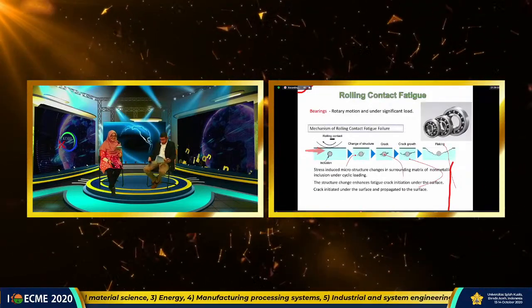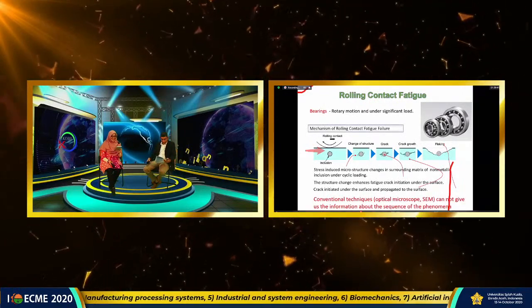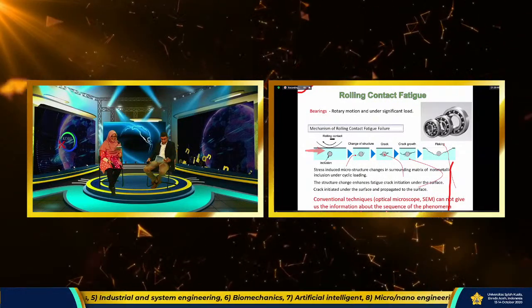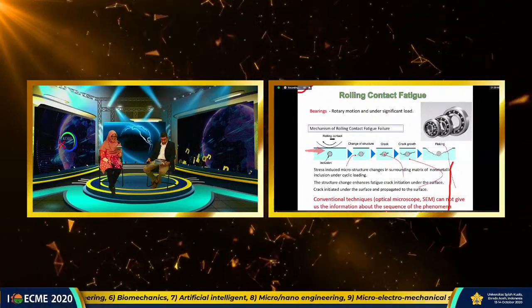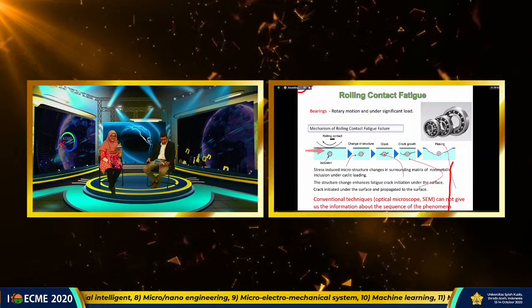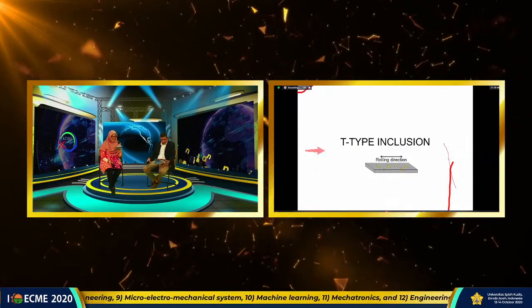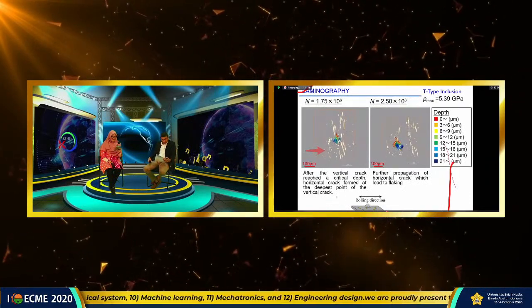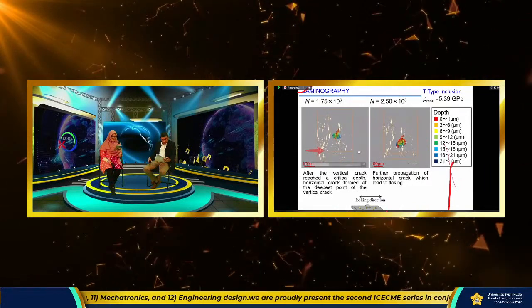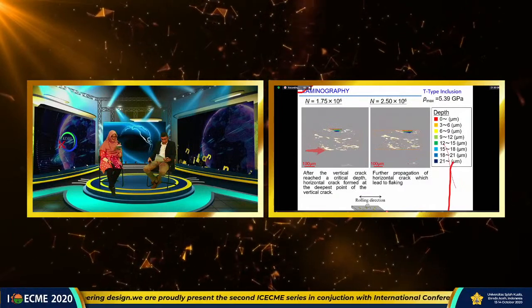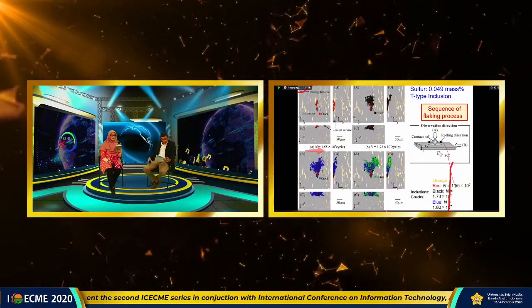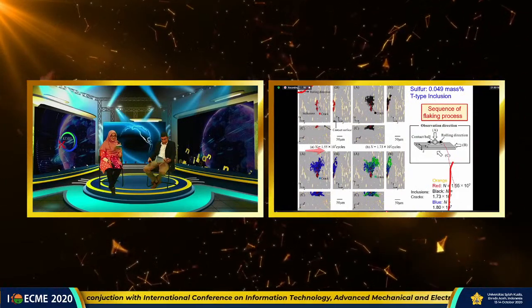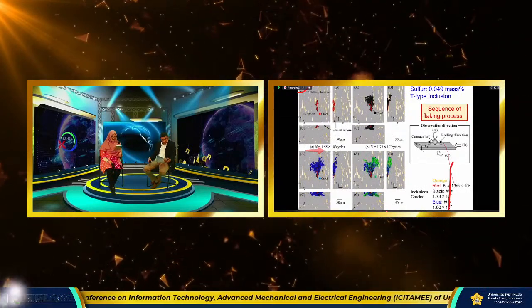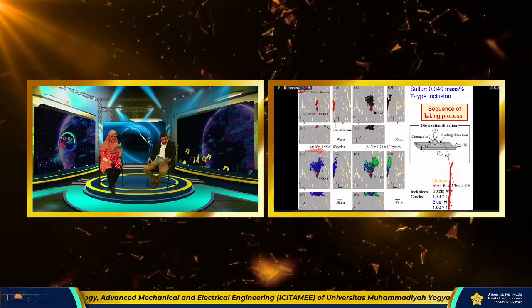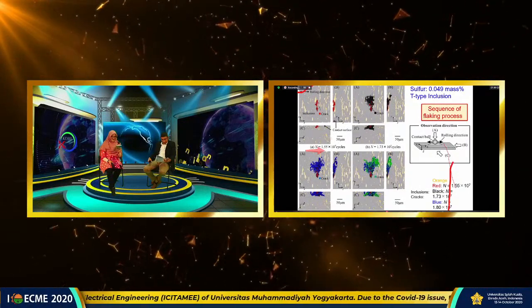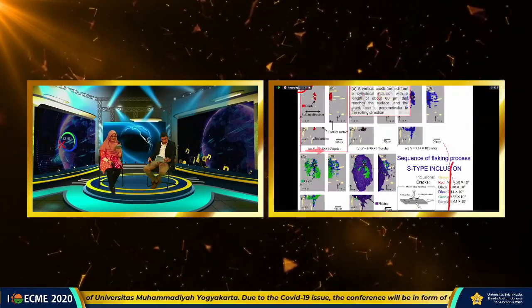So I skip this one. The mechanism of rolling contact fatigue is not observed directly by conventional microscopy, so we employ the synchrotron method. This is an example of cracks like this. You can see crack initiation like this. So the sequence is like this. Crack initiated from the surface, and it grows in the depth direction, and after that, for example, a crack forms at the bottom, the vertical crack like this. I skip this one.